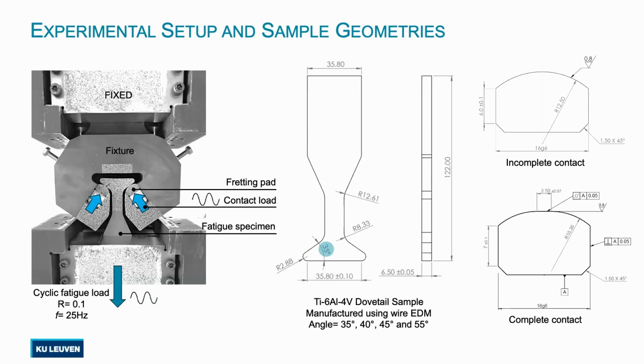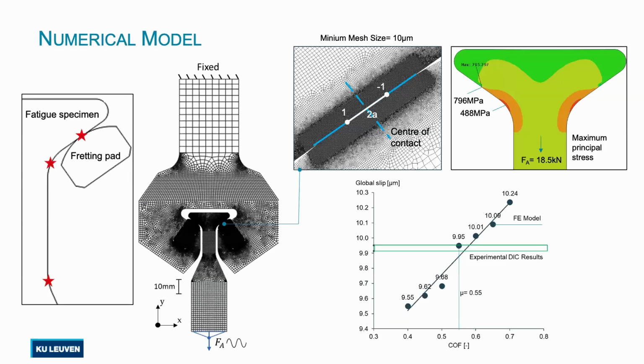And then we cycled the sample with a stress ratio of 0.1 and a frequency of 25 hertz. These contact loads are generated by the axial load, and that's why they are also cyclic. So this is the basic setup. We also developed finite element simulations just to control the load level. I'll tell you why we started with a finite element model: to find out the contact status at the contact interface, to avoid overloading or staying in the partial slip regime, which I will explain.